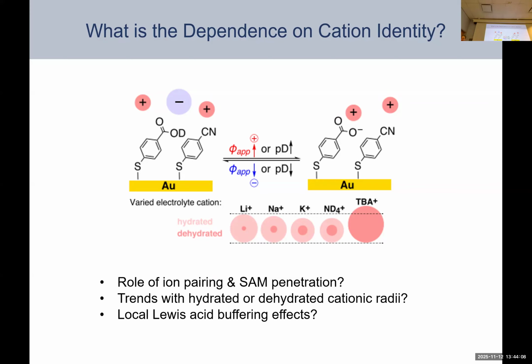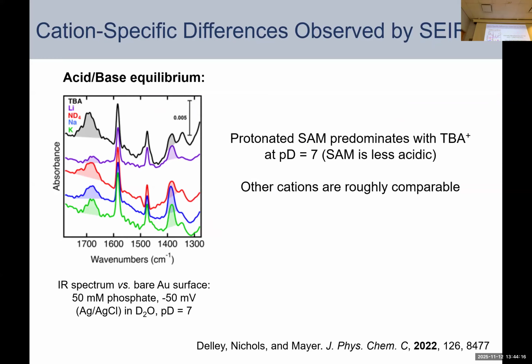So to try to understand the role of ion pairing and maybe SAM penetration of these cations, and whether there might be a trend with either the size of the hydrated or dehydrated radius, we again turned to SEIRAS. So here you can see these are, again, ATR-SEIRAS spectra of the mixed SAM in the presence of different electrolytes. Recalling that this wide feature around 1700 is illustrative of the carboxylic acid, the protonated form. Okay, and this peak here is reporting on the deprotonated form. You can actually right away see that with tetrabutyl ammonium, this is maybe the most clear trend here, that the SAM is dramatically less acidic. Okay, and these are illustrated at pD 7.